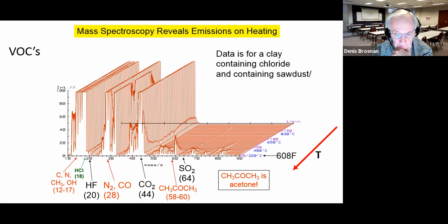Some other things like HF are shown out here. HCl seems to be high all the way along as we're having CO2. That goes with the fact that the carbon was burning and the hydrochloric acid was also coming out at the same time. But you begin to see some more complex molecules being evolved out here. And these are things that were certainly not present in the ceramic composition, but they are things that are evolved in firing of the ceramic.